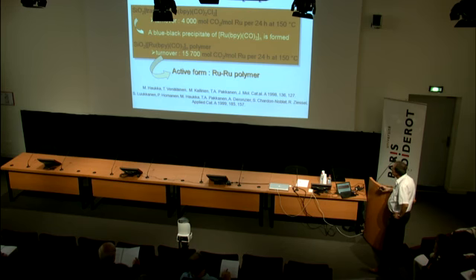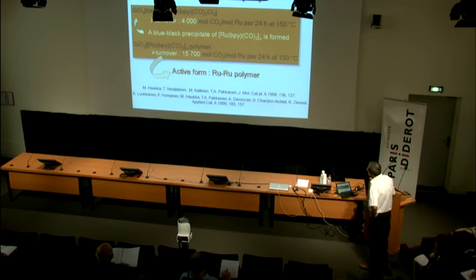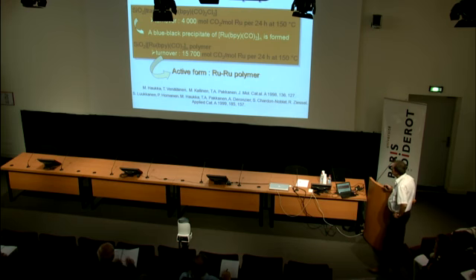And we have demonstrated that this polymer is very active for this important water-gas shift reaction. Water-gas shift reaction is the action of water with CO to go back to CO2 and hydrogen. Why were we interested in that? Because initially our colleague in Yonsei demonstrated that this complex itself is active as a catalyst of that reaction, and they observed a blue-black precipitate, and we demonstrated with them that in fact the catalytic species is the polymer formed in situ during the process.